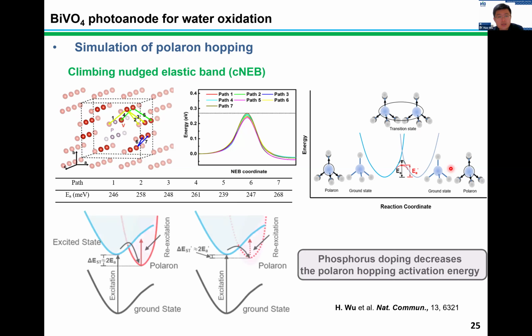And also we determined their binding energy, or the energy position of polaron states, and we found that upon the phosphorus doping, we uplifted the energy position of the polaron. It suggests that the charge or the electrons confined within the polaron states require less energy, or are much easier, to re-excite back to the delocalized band states and move forward. So this is the first time for us to report that phosphorus doping can decrease the polaron hopping activation energy and in turn increase the charge transport behaviors.